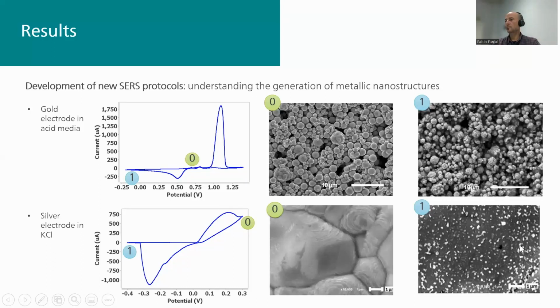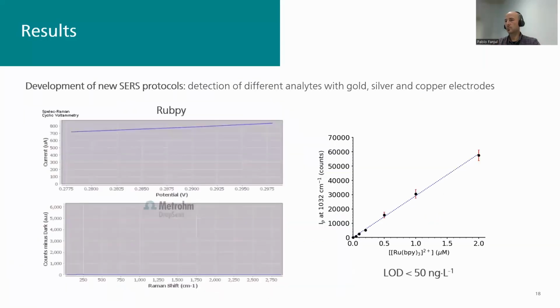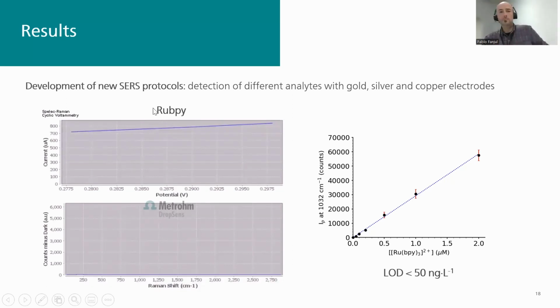And then these metallic particles that we generate in situ are the SERS active material for our quantitative assays. So now I will show you again with a video, so it's easier to understand what I'm talking about. This is for the detection of a specific molecule, ruthenium bipyridine. And this ruthenium bipyridine is adsorbed on the surface of metallic silver once the electrochemical pretreatment of the electrode is